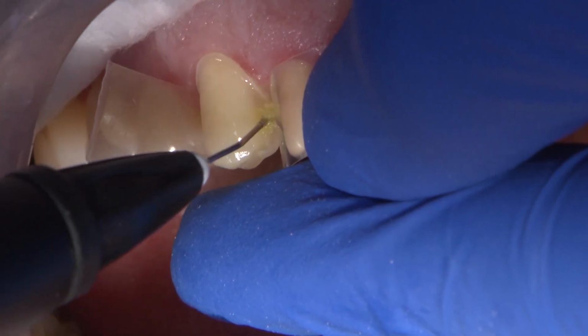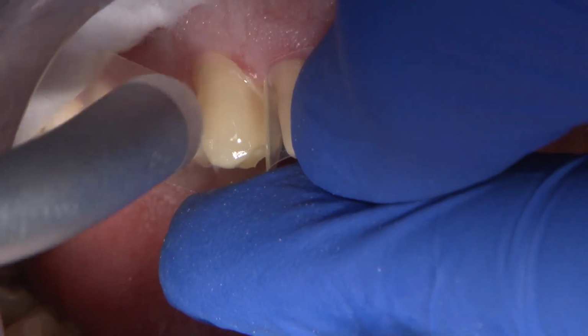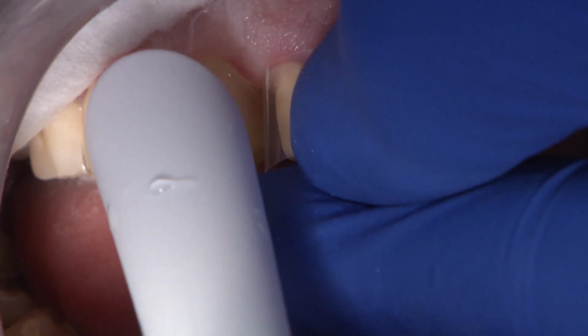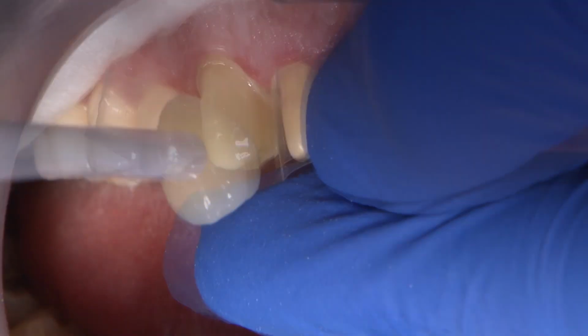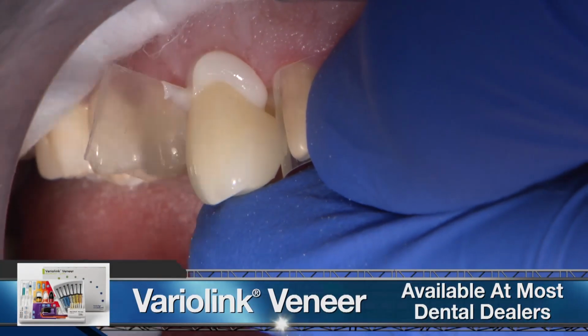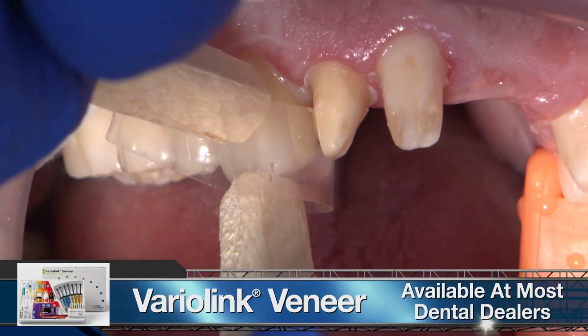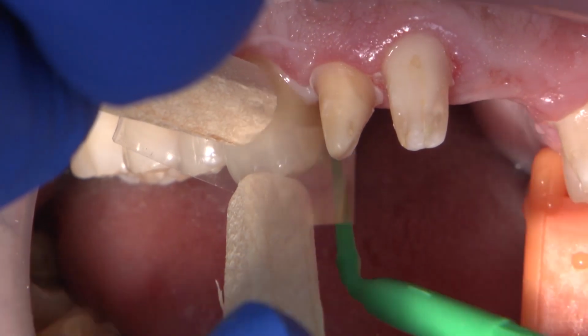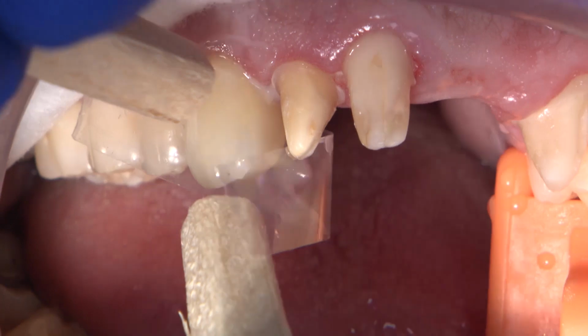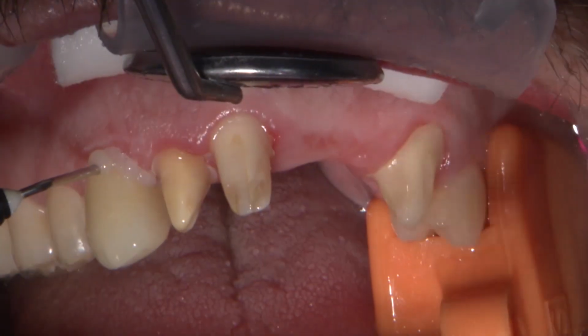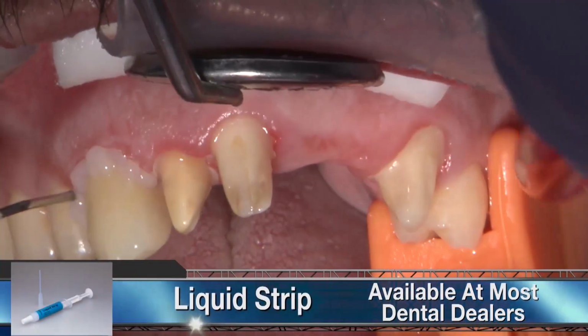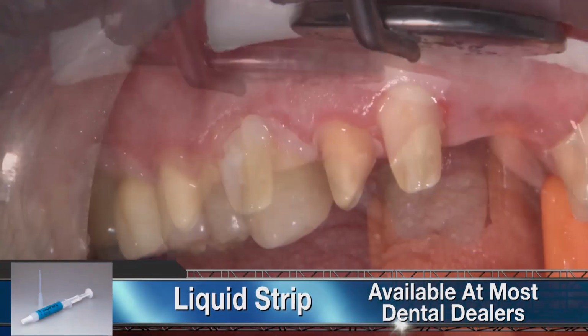After the inner surface of the veneer was cleaned and silanated, Variolink luting composite was applied onto the intaglio surface and the veneer was seated with light pressure using wooden sticks. While light pressure was maintained, excess cement was removed with a microbrush and briefly light cured so excess could be easily removed with hand instruments. Liquid strip was applied to create a good marginal transition without an oxygen inhibiting layer. Final polymerization was completed and then liquid strip was rinsed off with water.